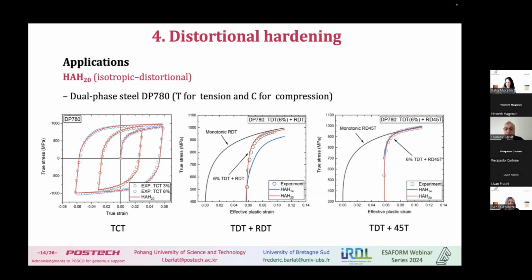And the last curve is tension in transverse direction followed by tension at 45. And here you see both models actually. The 20 and 14 are both matching the experiments well. So with this model, we're able to represent a number of experiments, reverse loading, cross loading, and we expect that everything in between, either between cross-loading and monotonic loading, or between cross-loading and reverse loading, so it looks like we probably would be able to capture most of the possible loading.